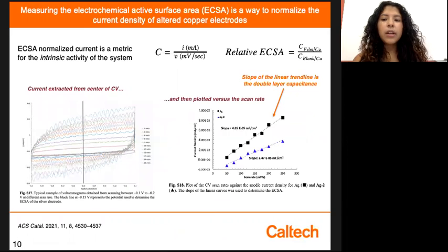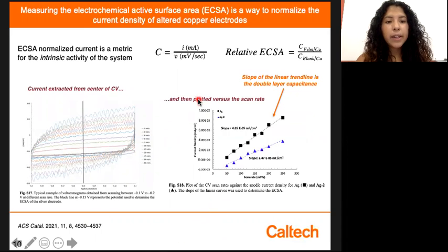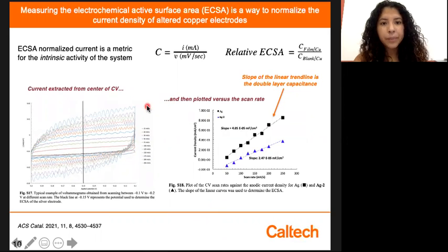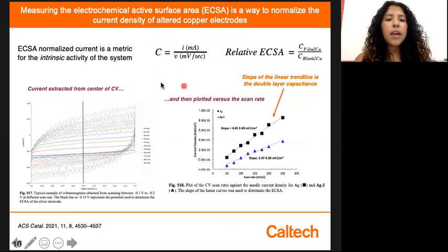And in order to understand the intrinsic activity of the system, a metric that was determined from the experimental data was the electrochemical active surface area, otherwise known as the ECSA. The ECSA is a way to compensate for changes in morphology due to the film or different copper surfaces. An ideal capacitor would follow this relationship where you can find the capacitance by the current divided by the scan rate, to then solve for the relative ECSA using the capacitance of the film on the copper electrode divided by the capacitance of the blank copper electrode.